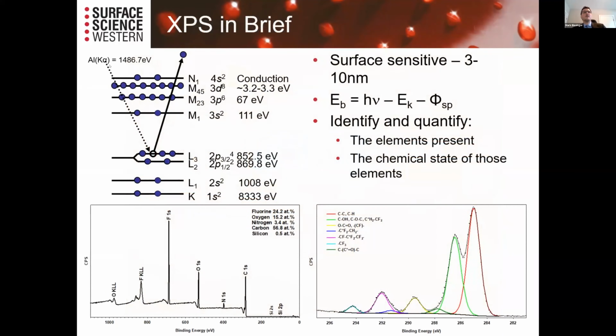XPS in brief, you start with X-rays, so aluminum K-alpha X-rays at 1486.7 eV. You knock out a photoelectron, you measure the kinetic energy of that photoelectron, and using the Einstein equation, you can calculate the binding energy of those electrons within the core of the atom. XPS is a very surface sensitive technique. You're looking at the outer 3 to 10 nanometers of the surface. And using it, you can identify and quantify the elements present.